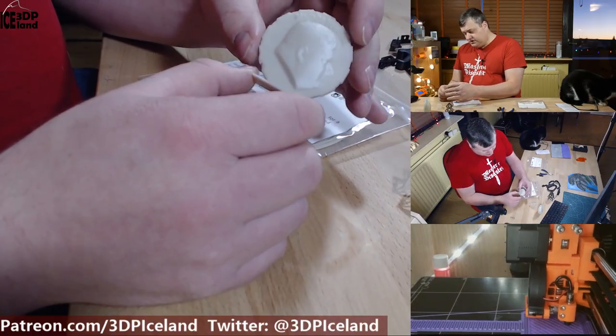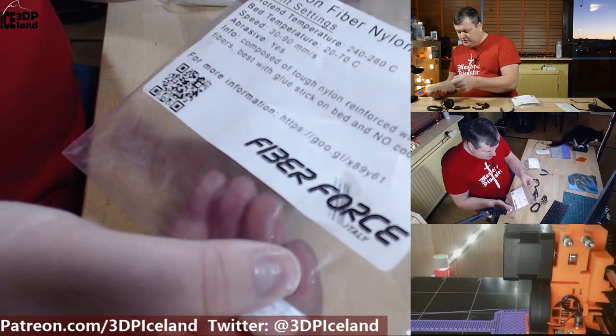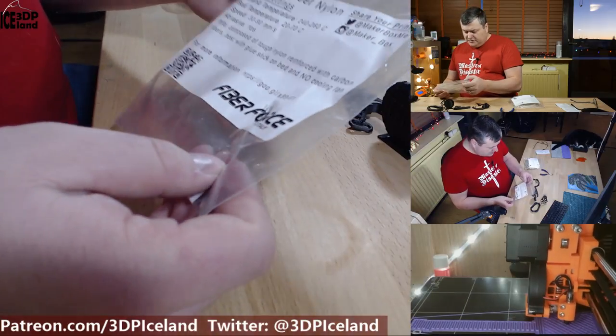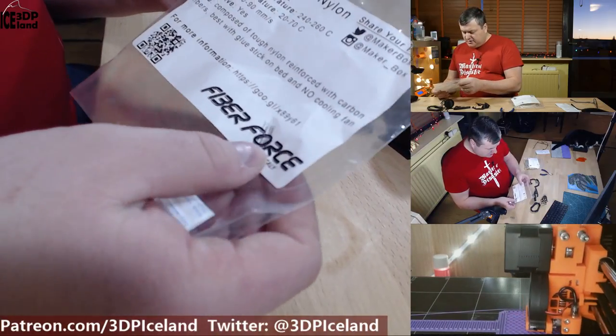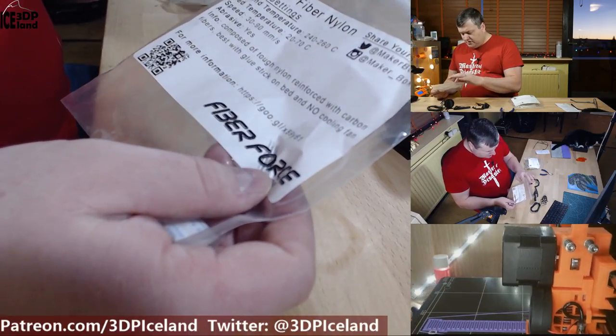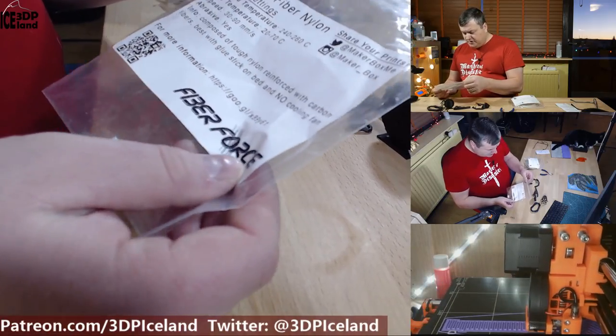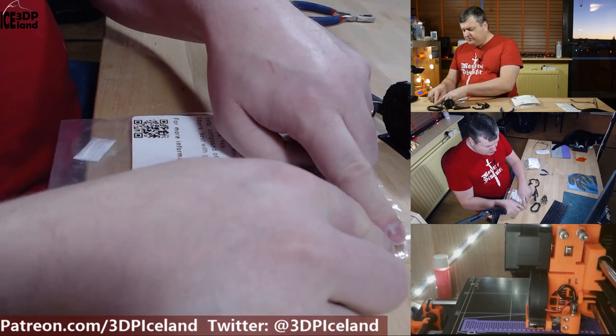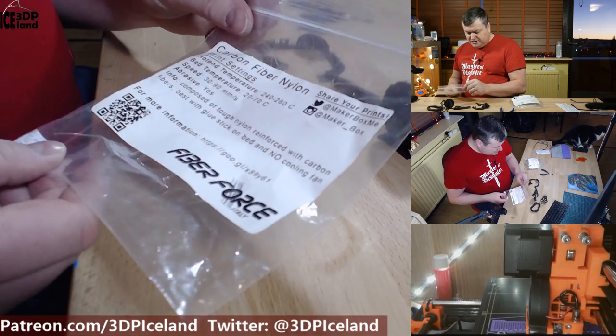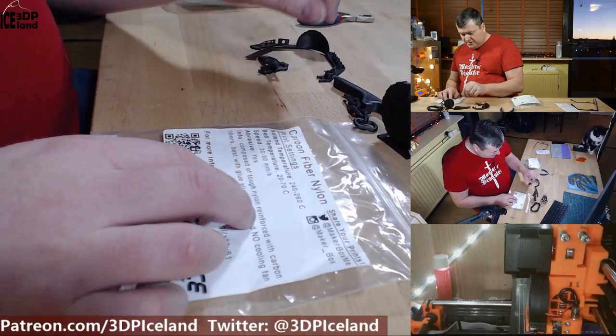The other filament I had for this video is carbon fiber nylon from FibreForce in Italy. This is also an abrasive filament and it prints at 240 to 260 degrees — pretty much ABS temperature. I used the ABS Prusa filament profile for those prints, and it prints with the fan turned off. So let's have a look at the samples.